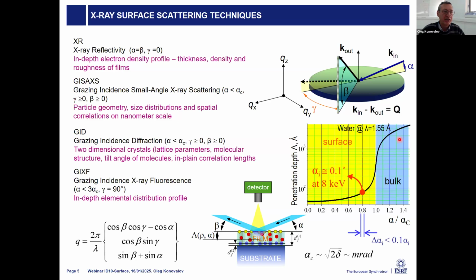And here as well, by changing the angle, we can change the penetration depth, and then we can excite atoms at different depths of our film, and measuring the fluorescence signal with the detector, we can see not only which atoms are near the interface, because here we can see really the elements. X-ray reflectivity is sensitive only to the number of electrons, but not to which atoms these electrons belong. But with fluorescence, each atom has its own fingerprint pattern, so we can discriminate it. By increasing the penetration depth, we can excite deeper and deeper layers of atoms, and from these curves we can get information about the distribution of these elements near the surface.